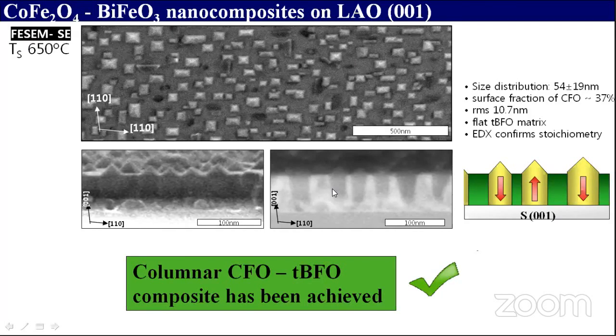Rather, when you put on strontium titanate, the cobalt ferrite was not growing this cleanly. So by changing the substrate, by changing the lattice strain, we can tune the crystal structure of the perovskite, and also we can have a very clean interface, which will improve your elastic coupling between your ferroelectric and ferromagnetic material. In turn, that will improve your magnetoelectric coupling.